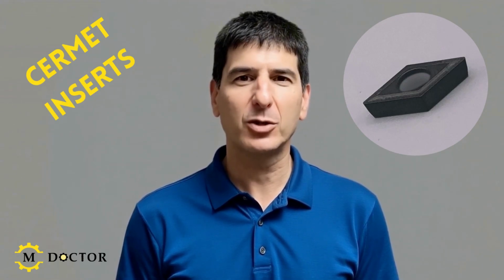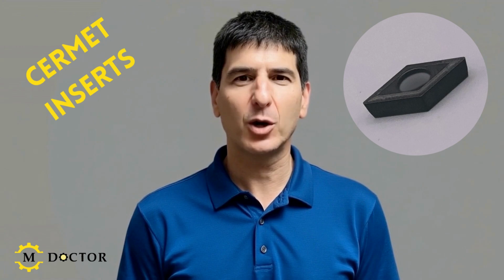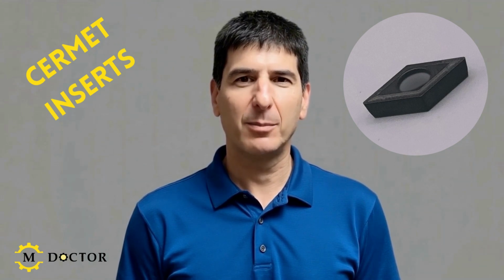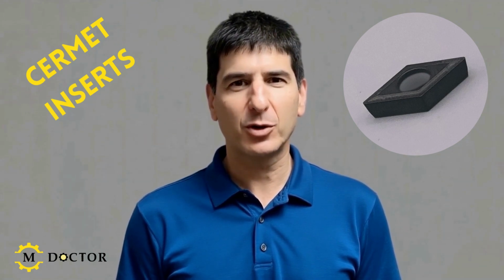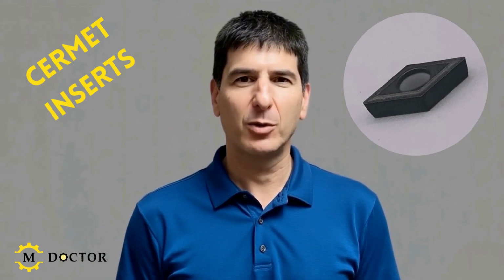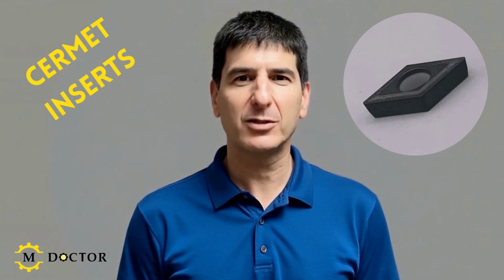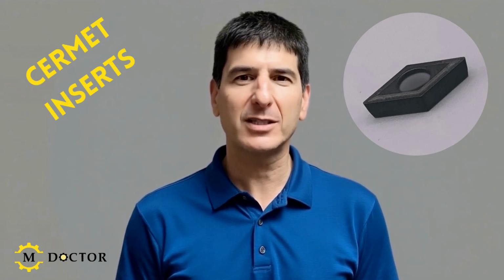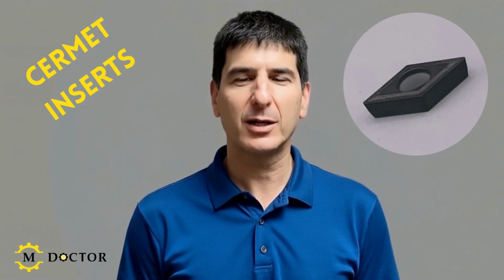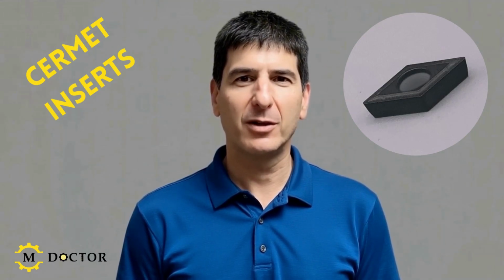While it's not considered an advanced material, another non-carbide option worth mentioning is Cermet. As its name suggests, Cermet combines ceramics and metals, usually nickel. This creates a substrate harder than carbide, enabling higher cutting speeds and better wear resistance. However, the very low toughness limits Cermet to finishing applications under very stable conditions. It works best for finishing operations and turning of steel and sintered metals. In these cases, you can run 10 to 20% faster than carbide while achieving better surface finish.